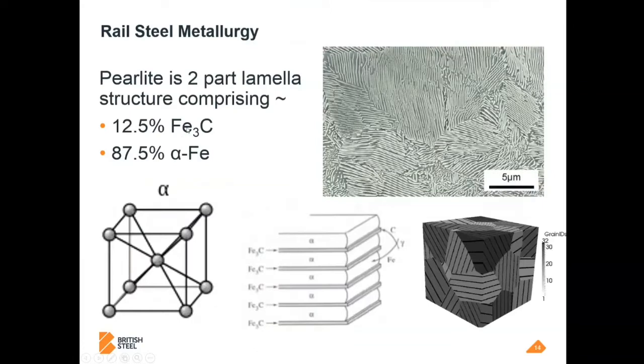So pearlite then, we've talked a lot about pearlite. Why is pearlite the preferred microstructure? There are a lot of metallurgy-minded people on this call, and I won't bore you with the details, but for those who aren't familiar, it's a two-part lamellar structure comprising cementite, which is iron carbide, and ferrite. It's like a composite material, and it forms at transformation, usually after hot rolling. We don't roll it as cold as that, so we finish at about maybe 980 degrees.